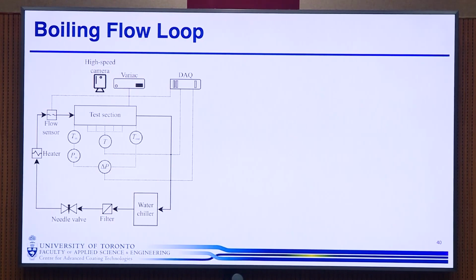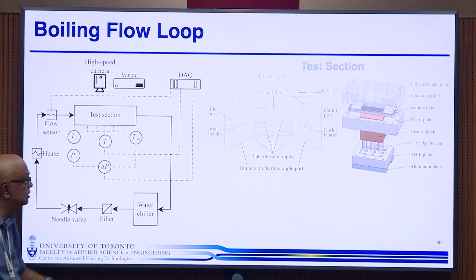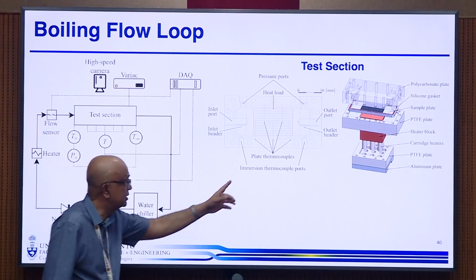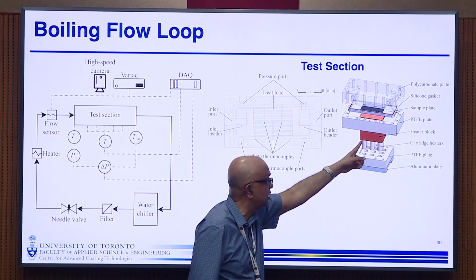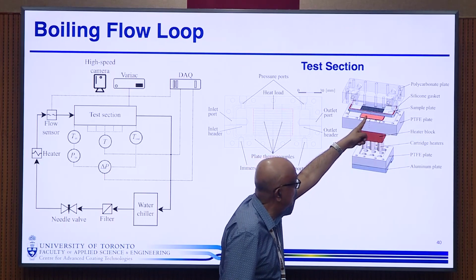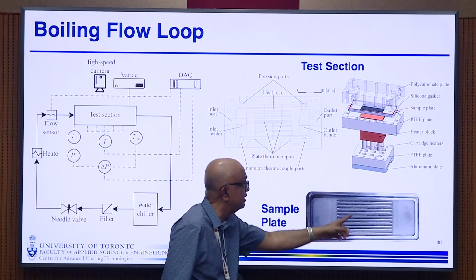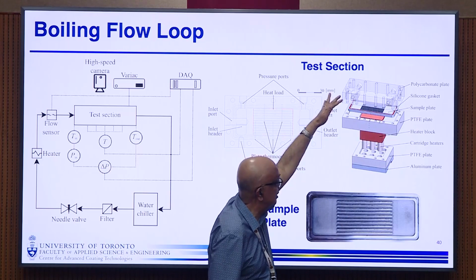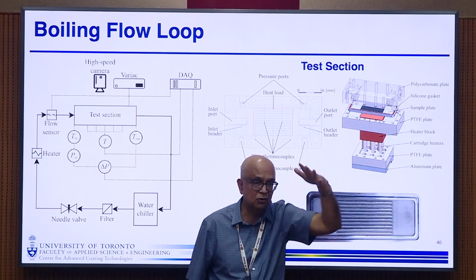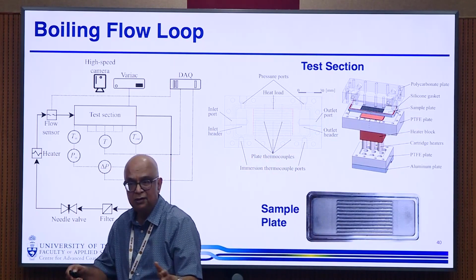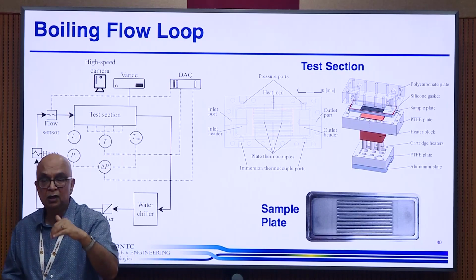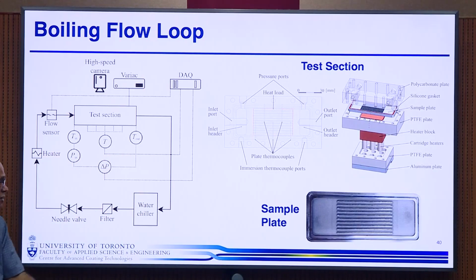Okay, so we wanted to go out and test this. We built a flow loop. This is a test section. We put a chiller, and we are running water through it. So this is what the test section looks like. We've again got a heater block. Over here, this is the sample plate. We put the sample plate over here, and then we've got a transparent polycarbonate plate on top, in which we can put all our headers, and we can also put our high-speed camera to look at it.